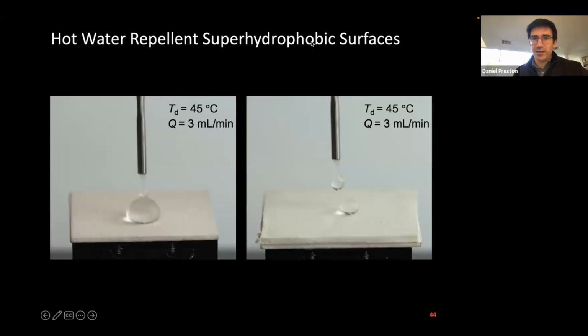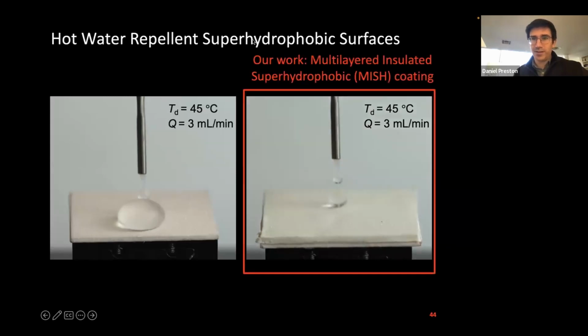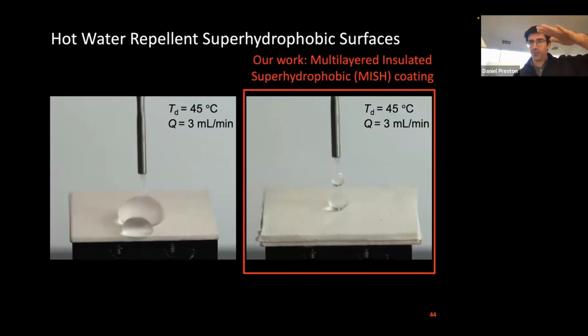And I'm just going to show on the right our proposed solution. So in this case, we have, again, the 45 degrees Celsius water impinging on a surface. We're calling it a multi-layered insulated superhydrophobic coating. And in this case, we have not just the spray-on superhydrophobic coating, but also a thermally insulating barrier beneath that superhydrophobic coating that helps prevent the evaporation and recondensation from happening by limiting the amount of heat transfer that can occur to the coating. And so this video is showing, hopefully, that it works much better than the one on the left, just the superhydrophobic coating.